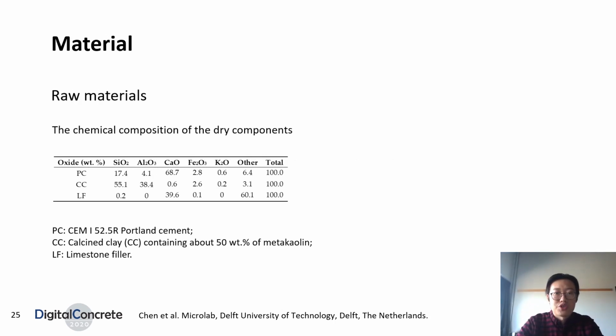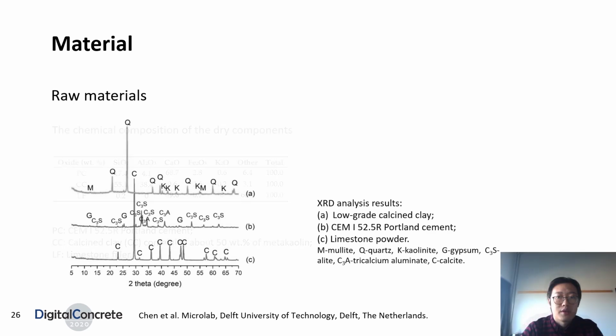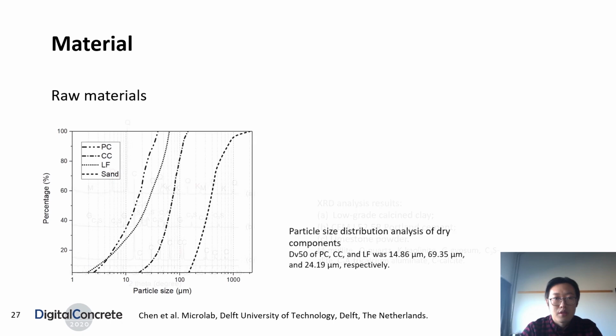For the material section, the chemical composition of binding materials, including Portland cement, a low-grade calcined clay that contains about 50% of metakaolin, and the limestone filler were characterized by XRF, XRD, and particle size distribution. It is worth noting that the calcined clay used in this study shows a coarser particle size compared to the others.